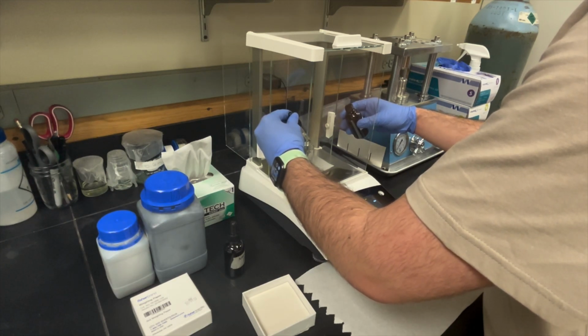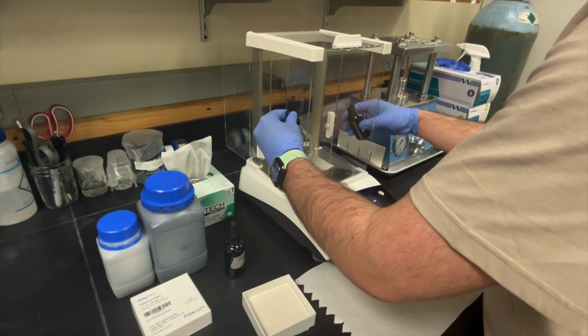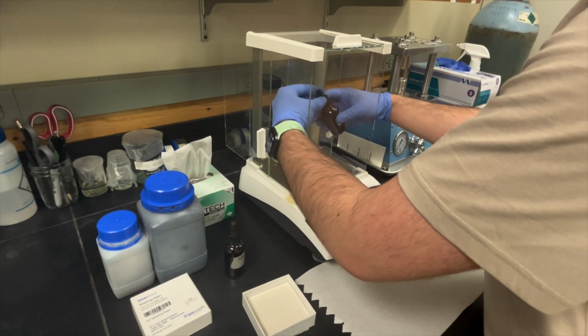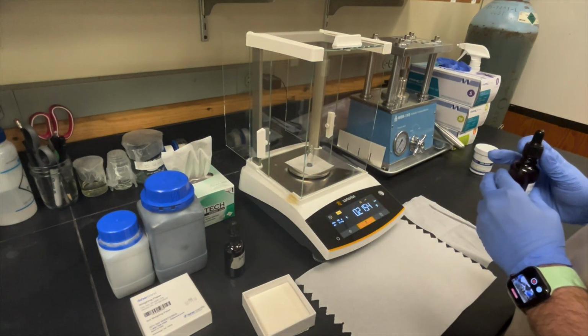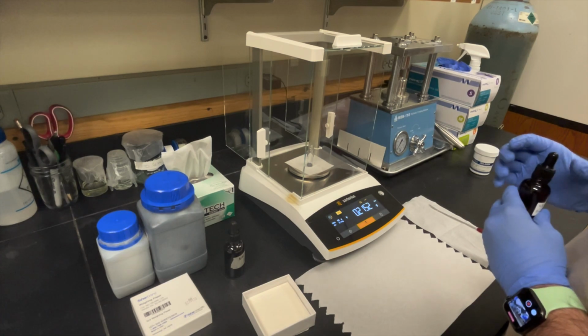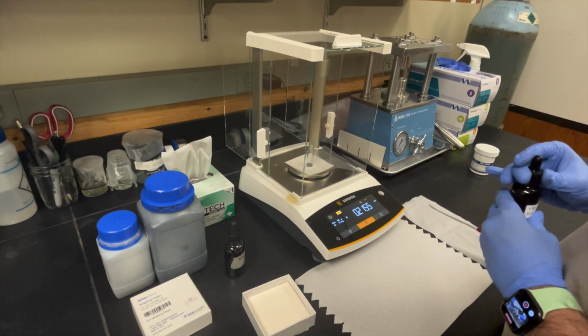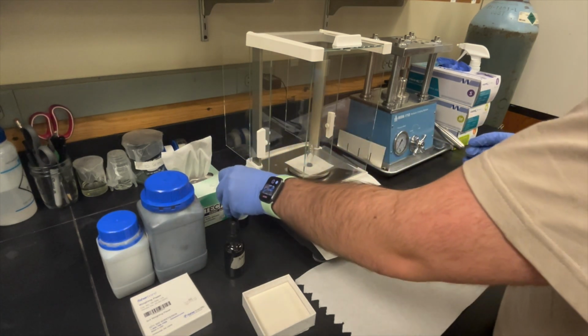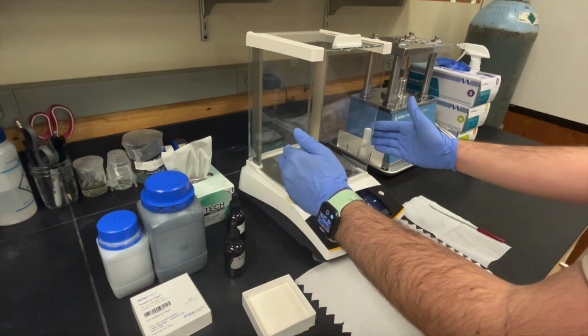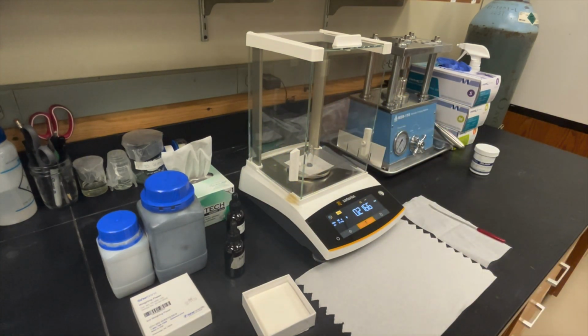For the binder solution, it may be better to be under the target mass rather than over, since the other powders are already likely lower than the target. In this way, we can attempt to keep them more equalized. We will also want to keep track of this number as well, and then calculate 5% of that for the PVDF.